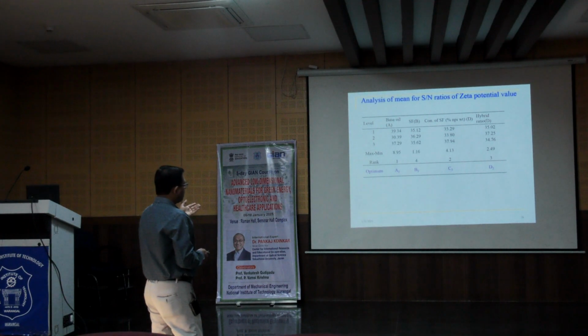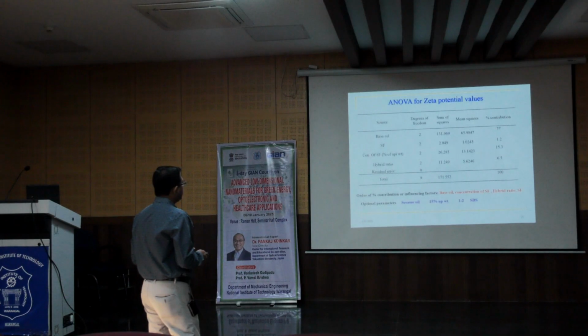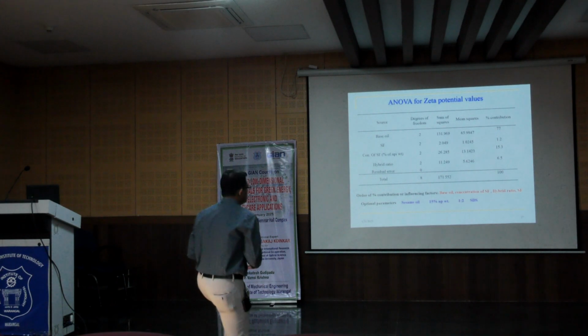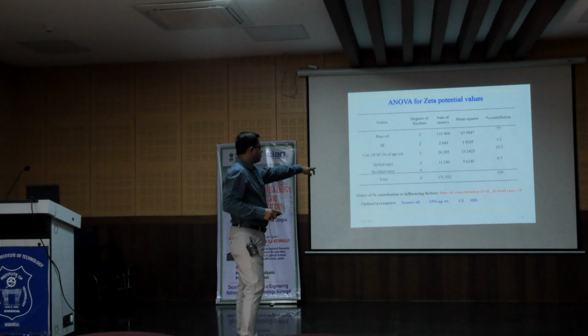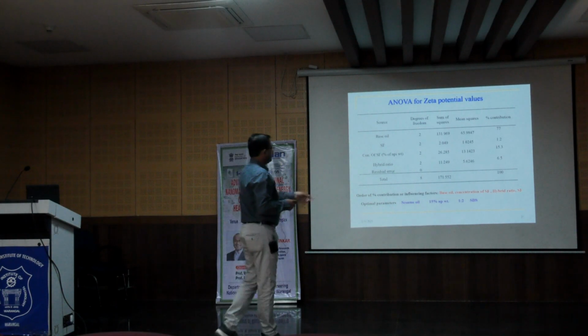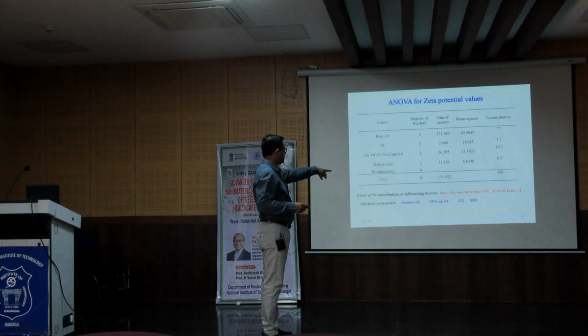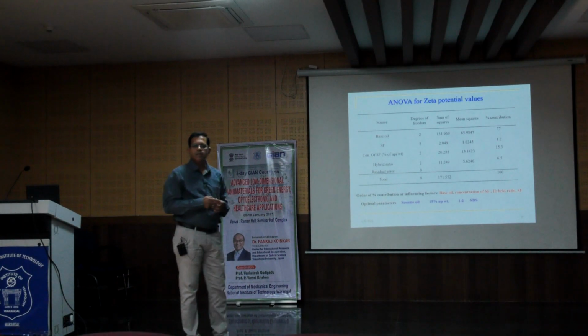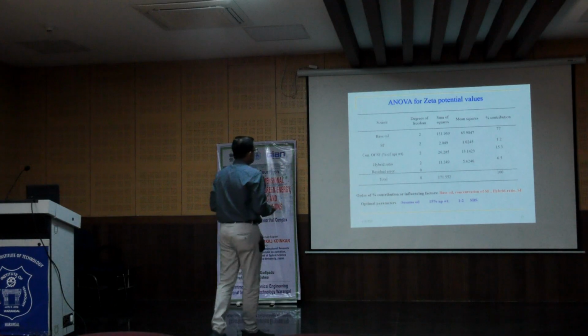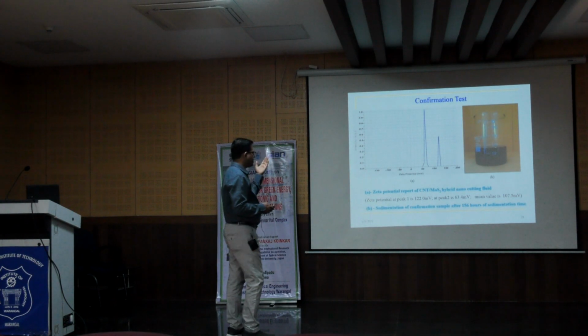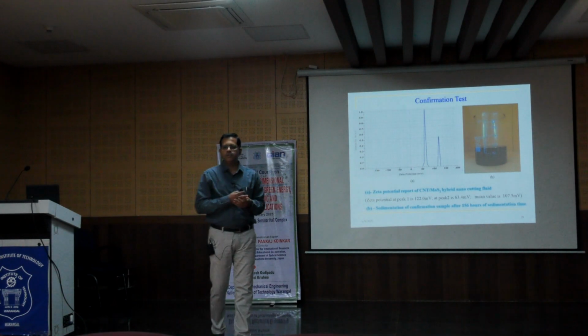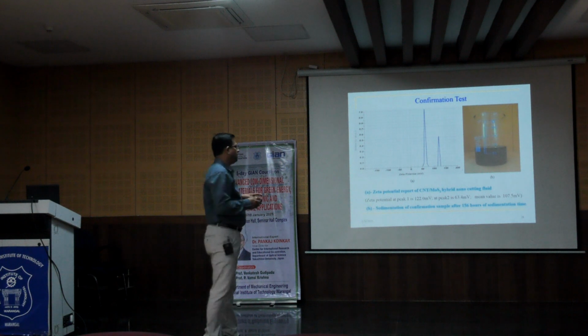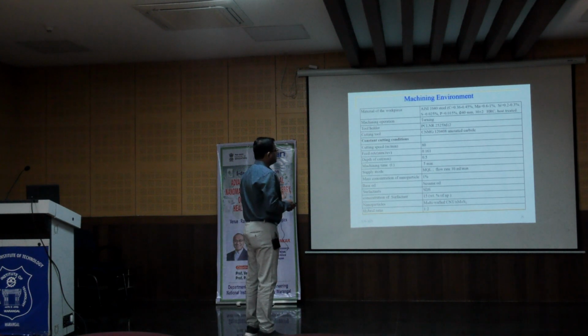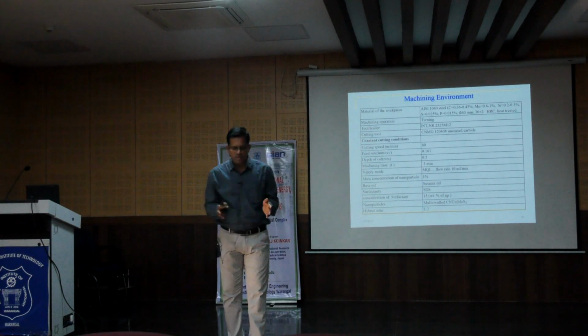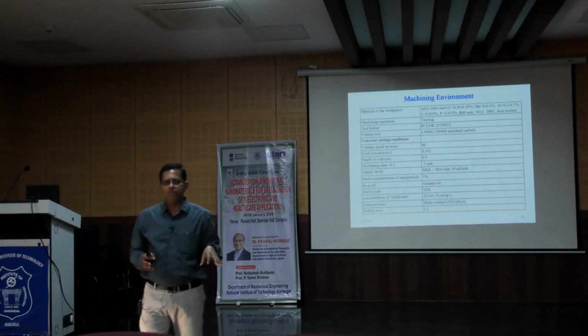So then we took the S/N ratios, etc. And finally we got the optimum: the base oil is sesame oil, the particle percentage is 1:2, that is CNT and MoS2, the surfactant is SDS, and the surfactant percentage is 15% of the nanoparticle weight. Then, for confirmation, we prepared the same composition again, and tested for sedimentation as well as zeta potential value, so that once we confirm that, we go for machining. In the actual machining environment, we are going to use this hybrid cutting fluid.